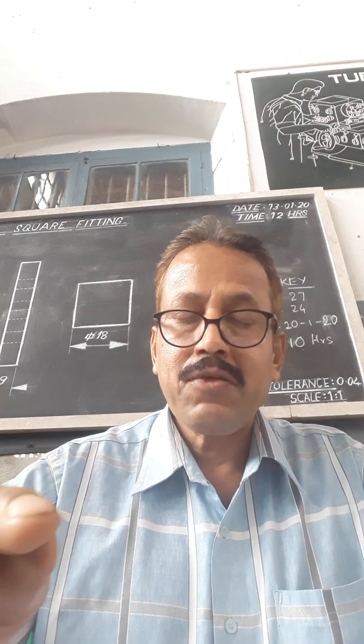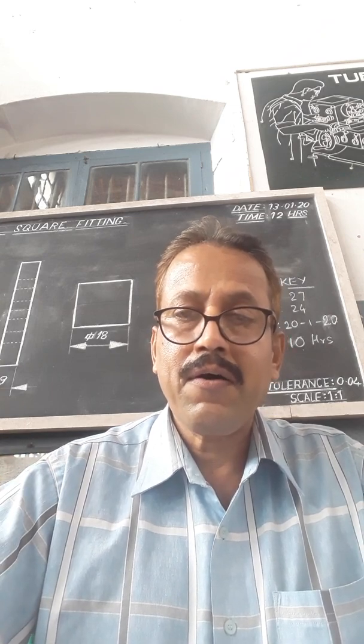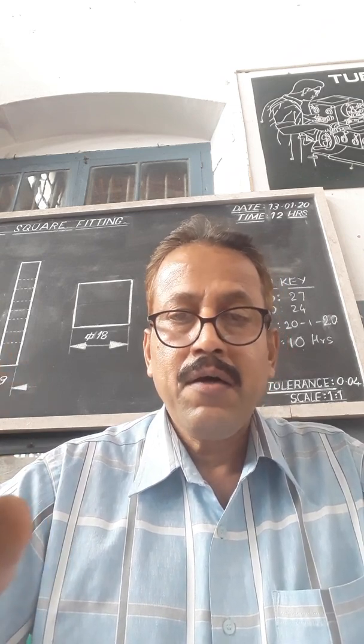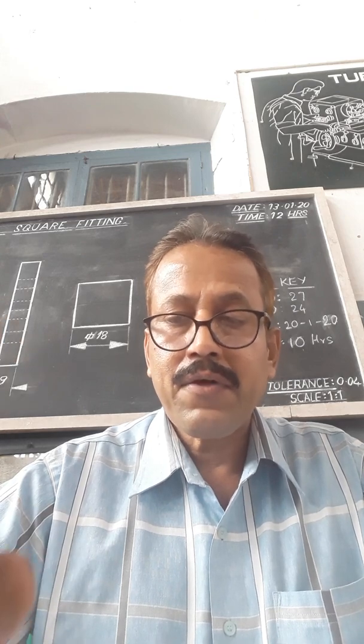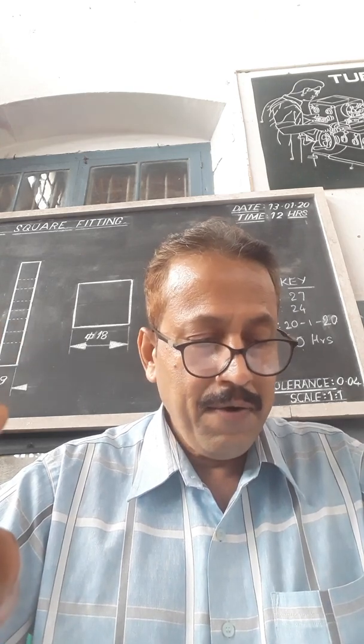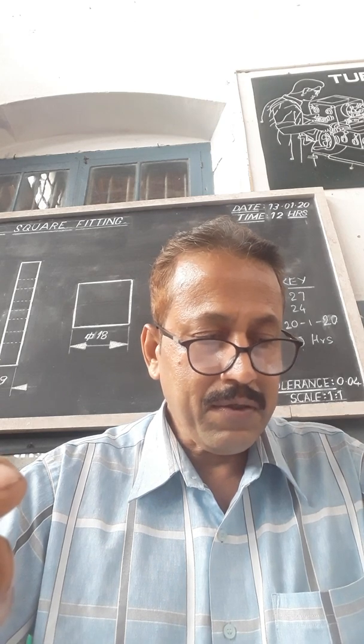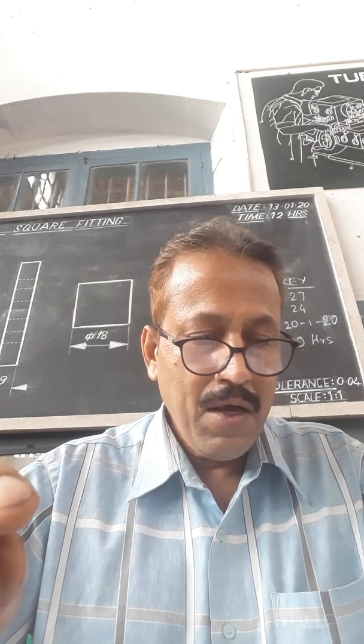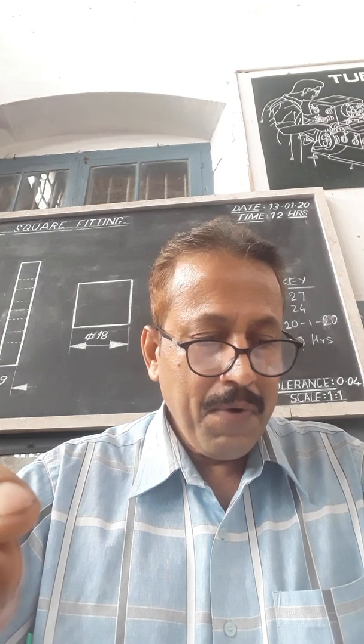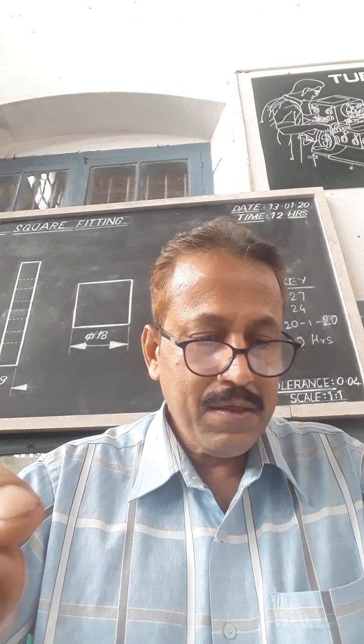If we touch it, our hand sweat may get on it, and there are chances of rusting the slip gauges. If available, use protector slips on exposed faces. After use, clean the slip with carbon tetrachloride and apply petroleum jelly for protection against rust.